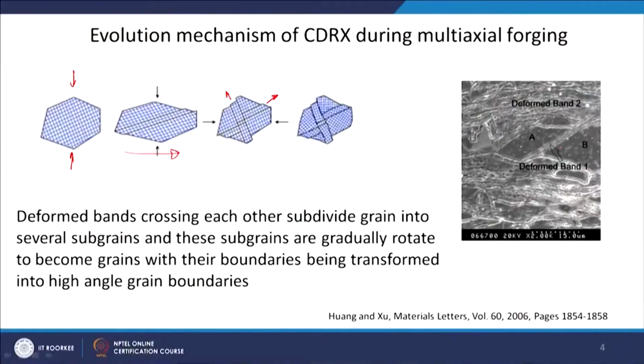Then again we will change the direction of the forging. Again a new band will be created which will cut all the previous deformation bands and so on. And one example of deformation band is shown here in the micrograph. So, this is a big grain, which is sheared into A and B two parts through the deformation band here. Now you can see the smaller subgrains will form, and these deformation bands consist of high dislocation density. So, you can consider it as a low angle grain boundary.